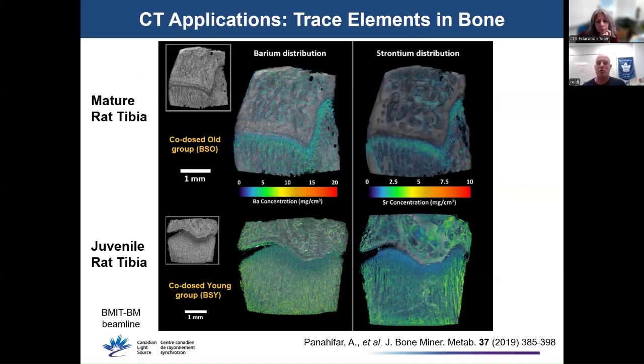For the mature rat bone at the top row, most of the barium and strontium are incorporated in what is called the growth plate, which I've illustrated here with the red arrows. For the juvenile rat bones in the bottom row, barium and strontium are almost everywhere because the rat is still growing. So this work shows the potential for using these trace elements as contrast agents, and you can use them to track changes in bone growth for pharmaceutical studies to see how drugs that are promoting bone growth work and compare them to placebos and things like that.